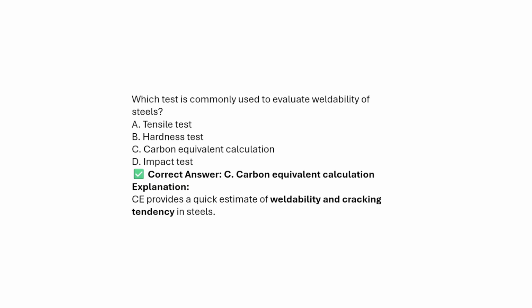As you have seen, if the carbon equivalent increases, it will result in poor weldability. So we want to avoid that. That's why we want to choose the material which has a low carbon equivalent, so that it will have good weldability. So the answer will be C. Carbon equivalent calculation provides a quick estimation of the weldability and crack tendency in the steel.